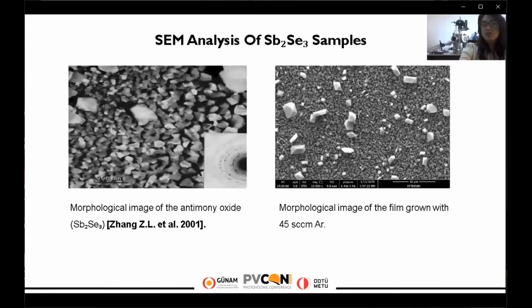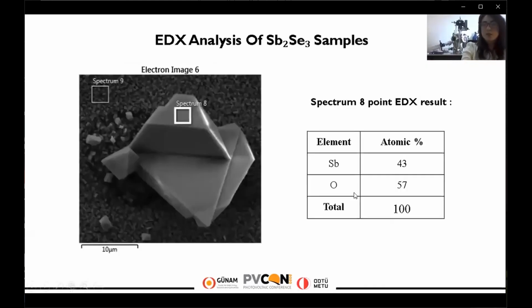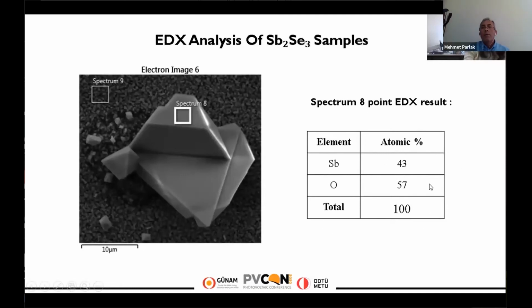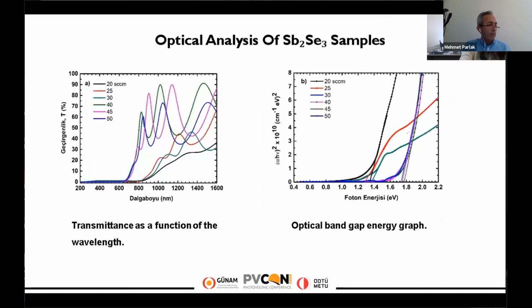When we close up on the image of the 45 SCCM argon sample, we have taken the point EDX analysis from spectrum 8. This bright crystalline structure belongs to the antimony oxide compound. It was detected by point EDX analysis. This case can be explained by the decrease in the selenium ratio, which is not desirable for the antimony selenide compound in photovoltaic applications, because selenium separates from the film surface during sputtering at higher argon gas rates.